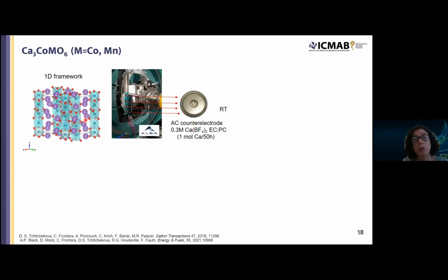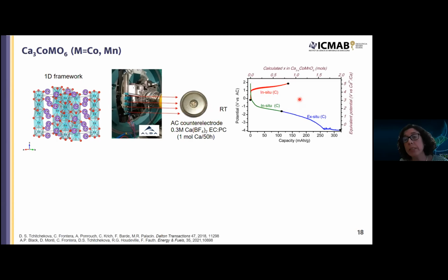We prepared this compound. It is really easy to prepare. This family of compounds has been studied a lot for its magnetic properties, with the intra and inter couplings between the chains and so on. And we were able again to do operando diffraction at the ALBA synchrotron using these coin cells at room temperature. And this is somehow the electrochemical curves that we get.